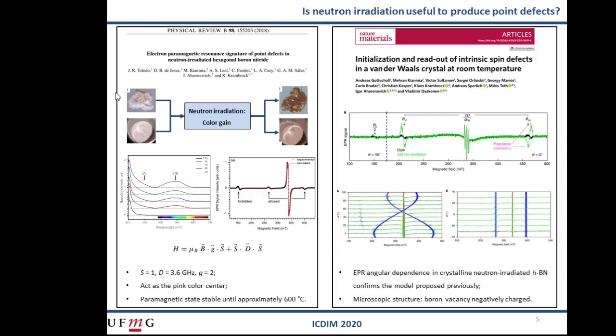The use of neutron radiation to produce point defects in hexagonal boron nitride is already known. In our previous work, this PRB here, we provide the first description of a high-spin center produced in powdered samples. This center is responsible for the pink color gain, here in this figure for example, in the samples after radiation, and by optical absorption measurements, here in this figure, we observed a broad absorption band covering almost all the visible region, with a maximal absorption around the green spectrum region, here.